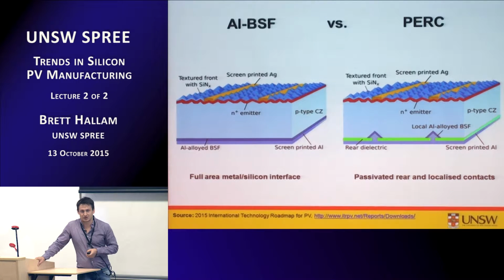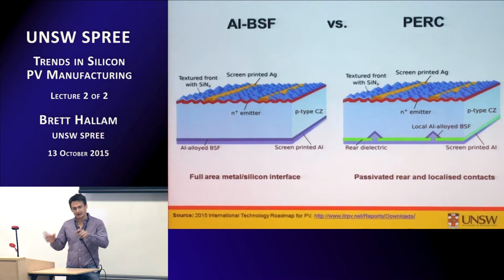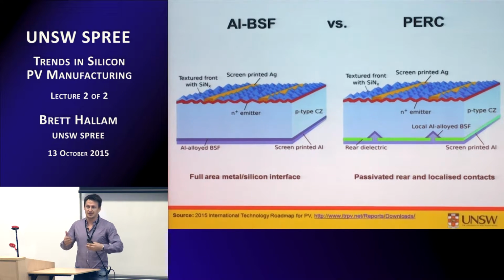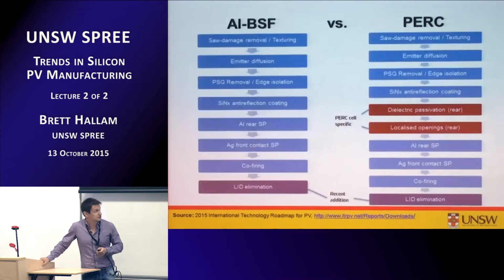Yes, exactly. So if we were to use exactly the same sheet resistance on the emitter, because we've changed the open circuit voltage, or more so the operating point of the solar cell, it'll actually change the series resistance within the device. That's one important thing to consider. Basically, anytime we make a single change in our device, we potentially need to completely redesign the entire solar cell. Because we've now put the surface passivation on the back, we've reduced the surface recombination velocity, we increase the voltage, potentially we need to adjust the front surface slightly. So either changing the sheet resistance, bringing the fingers in close together to counteract what natural changes will occur for the series resistance, to re-optimize the efficiency.